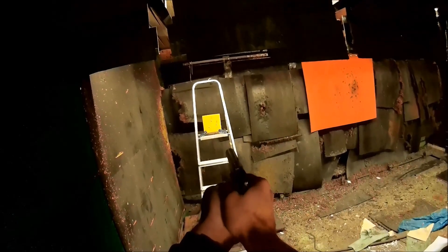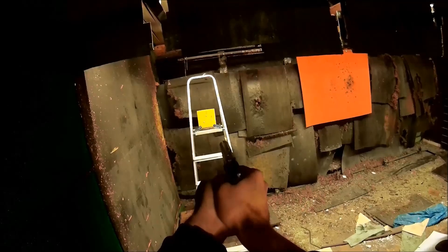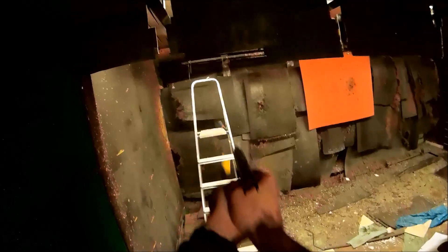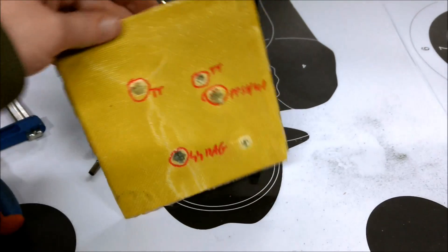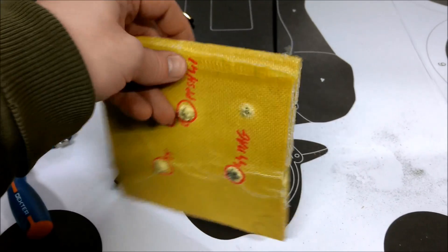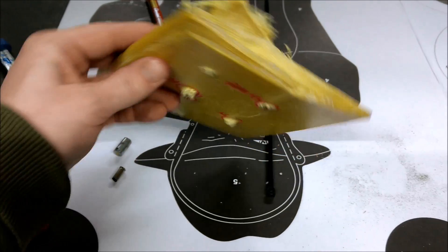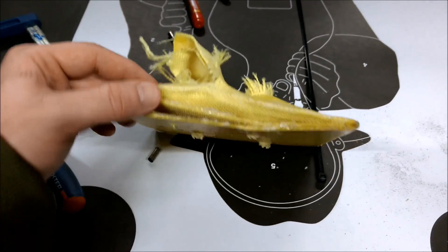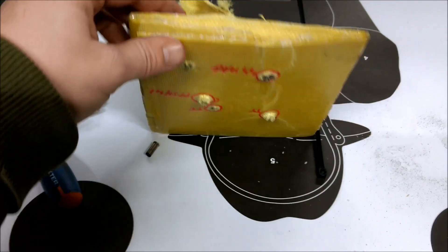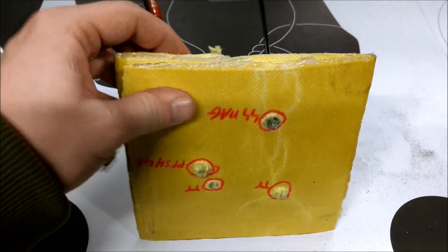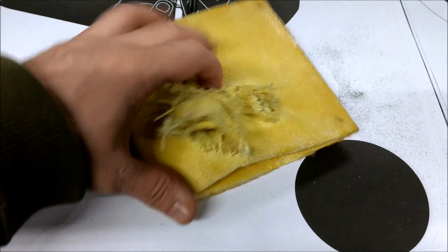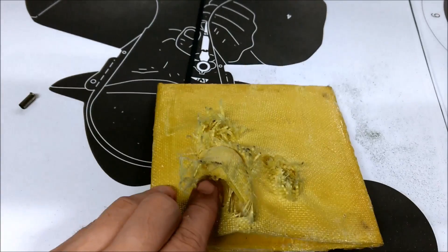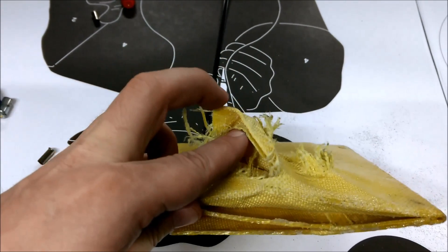Okay, so I managed to put a shot in that corner and basically rip the plate apart. And as you can see, all the layers delaminated. I didn't have a big area to shoot at, so like the other plate I did, it was more than twice big. The penetration is over here, and then it pulled all the layers and the bullet just fell out.